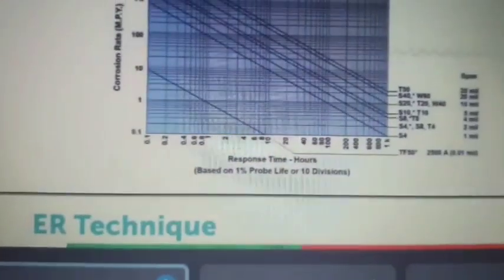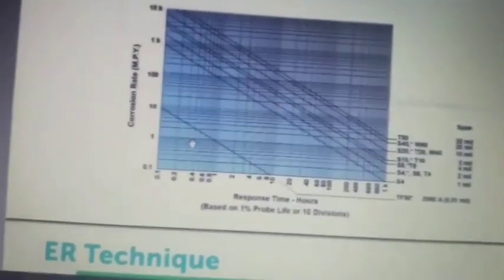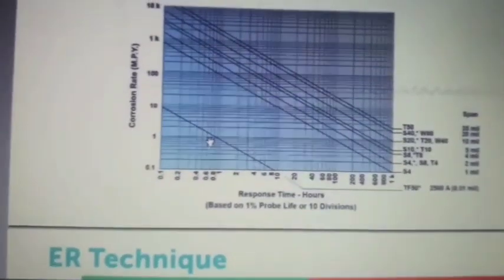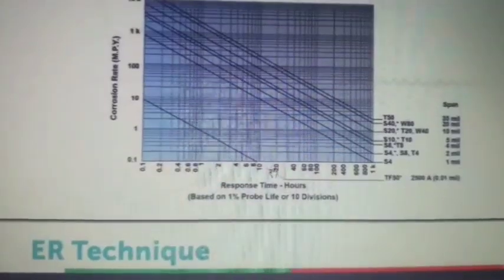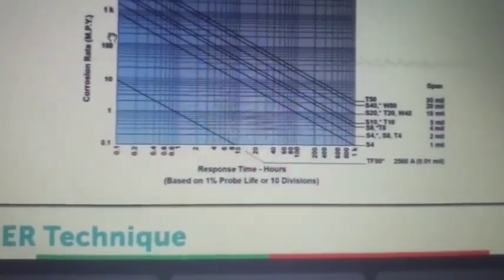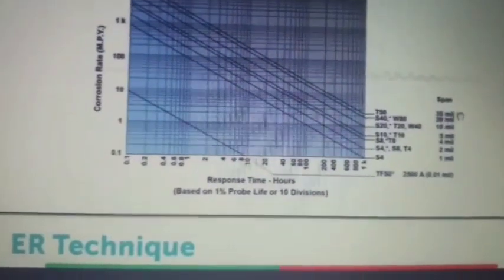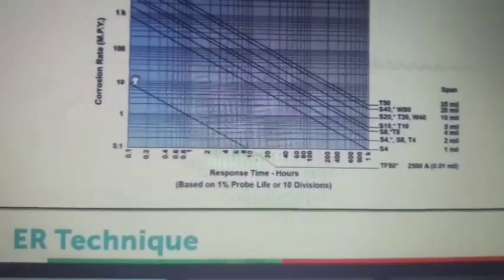If your system has high corrosivity, like 100 mils per year, this will not work at all because it will corrode faster. But this one will give you a reading within 20 hours. Whereas this one will not work at all because the probe will get totally corroded. So for a high corrosivity system, you have to use a thicker probe, whereas for a low corrosivity system, you have to use a high sensitivity resistance probe.